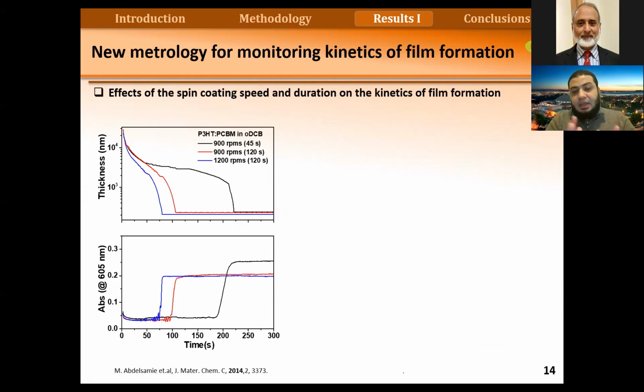So we applied the same thing to solar cells. We tried to use P3HT. We blended it with another material, which is an acceptor. So P3HT is used here as a donor. We also looked at the spin coating process. We tried to change the processing conditions.